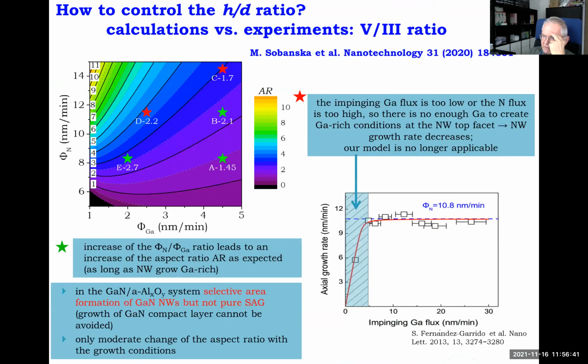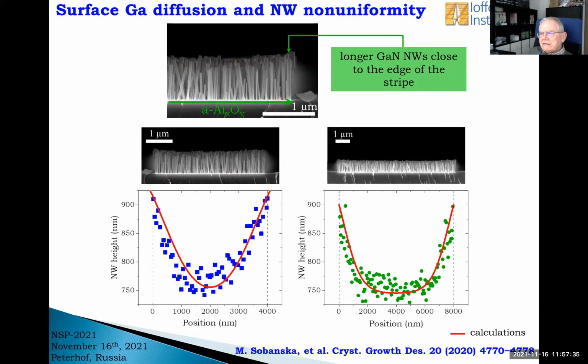One thing is important here. If you have a look at a cross section of such a stripe, you see that wires close to the edge of the stripes are longer than in the middle. So this is quite the opposite behavior to that observed previously. And here you have a plot showing how the length of wires changes with distance from the edge. This is the distribution across the stripe, and differences are pretty large, because the difference between the length of nanowires here and in the middle is something like 150 nanometers.